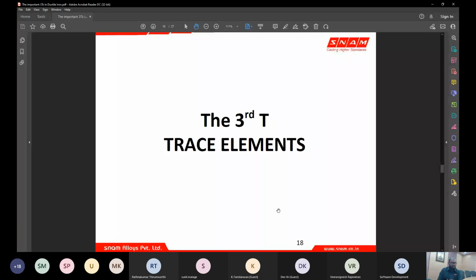So when we are able to control these two, do we guarantee that the casting is still going to be okay? No. There is one more part which is going to influence, even if your time and temperature are correct. So we have ensured that the time taken for the graphite to come out, the time taken for the nuclei to be stable, the temperature at which nuclei is going to be stable, everything is ensured and pakka, and we have monitored and maintained it correct over different temperatures, over different pourings. What happens if there are some tricky elements present in your liquid metal, which have entered into your liquid metal without your knowledge, and even with constant control over time and temperature, still lead to a defective casting?